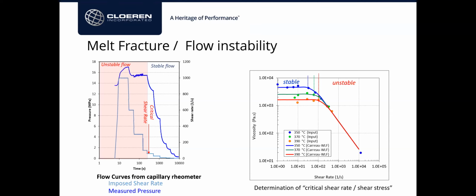Okay, next question. How do you do time sweep in capillary rheometer? Doesn't material leave instrument during the test? So we load the material in a barrel, we melt it, and then we would basically do a normal test, but we basically lock the test to one shear rate. So for example, I will take a shear rate of 20 and the piston is moving slowly. The material is flowing through the die and the pressure is measured over time. And so it could be over an hour, for example.